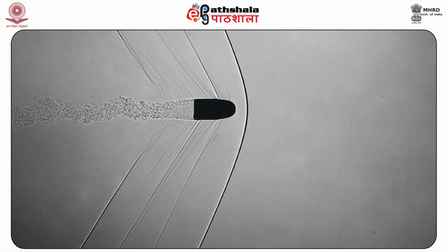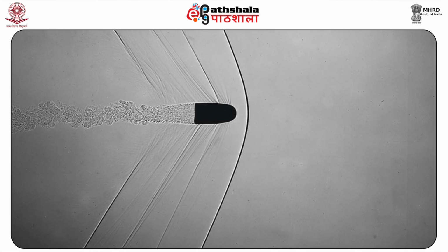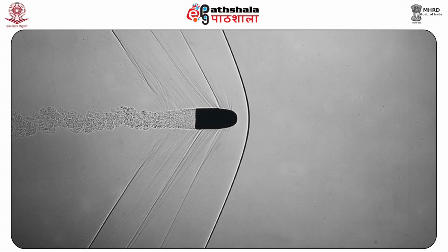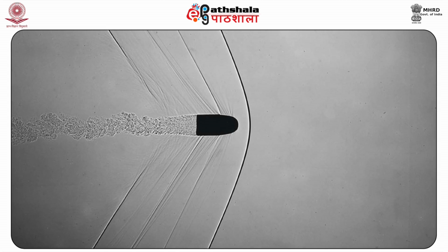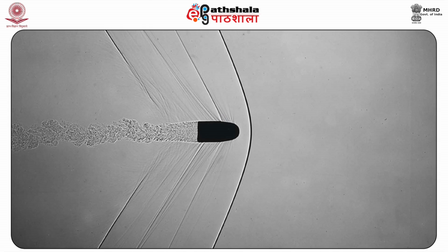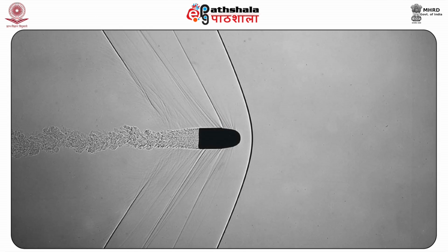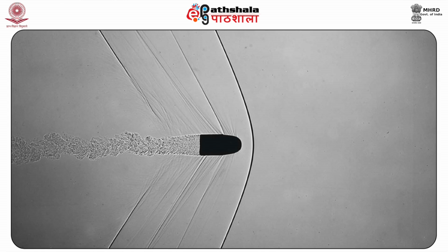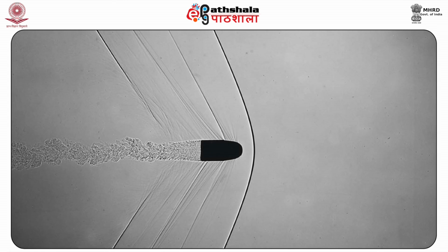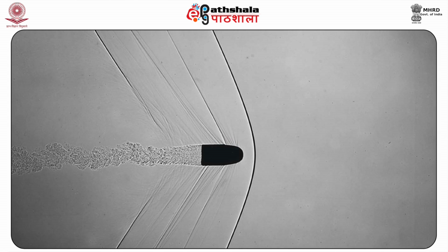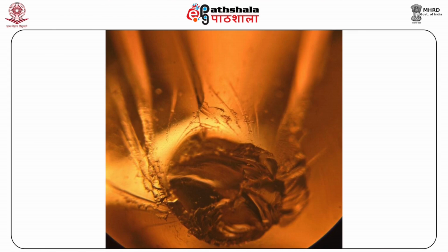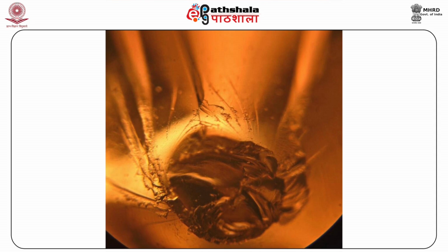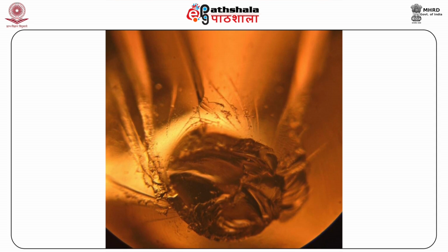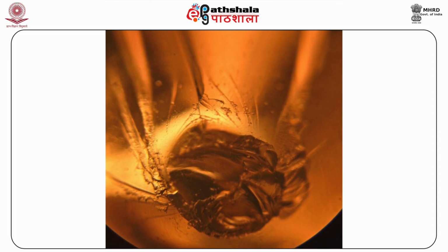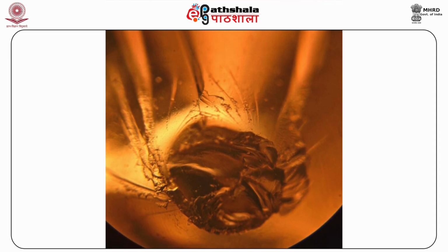High velocity impact fractures. A high speed projectile striking a piece of glass will produce a cone or crater. If the projectile passes through the glass, the opening on the exit side will be larger than the opening on the entry side. If the impact site is not preserved, the glass must be reconstructed to observe any coning effects.